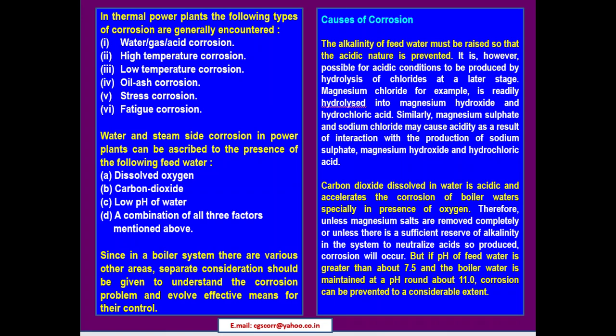Causes of corrosion: the alkalinity of feed water must be raised so that acidic nature is prevented. It is, however, possible for acidic conditions to be produced by hydrolysis of chlorides at a later stage. Magnesium chloride, for example, is readily hydrolyzed into magnesium hydroxide and hydrochloric acid. Similarly, magnesium sulfate and sodium chloride may cause acidity as a result of interaction, with production of sodium sulfate, magnesium hydroxide and hydrochloric acid.